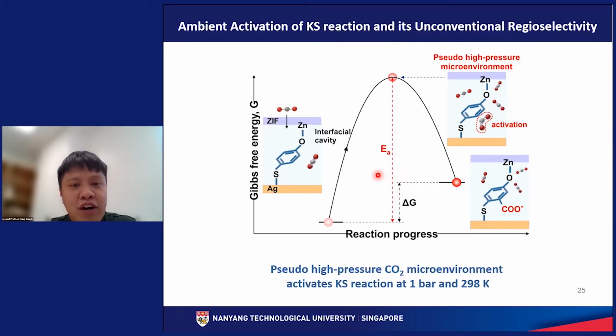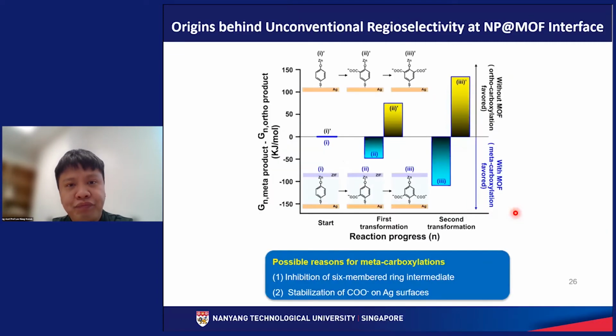Okay, so in short, continuous CO2 absorption into the interfacial cavity will create a pseudo high pressure microenvironment over here. So this will cause the CO2 to be bent. If you look carefully at most of the transition states involving CO2 molecules, they would typically involve carbon dioxide in a bent geometry. So this is a way for us to activate the carbon dioxide molecule. So subsequently, the reaction can flow towards the right side to form our carboxylate product.